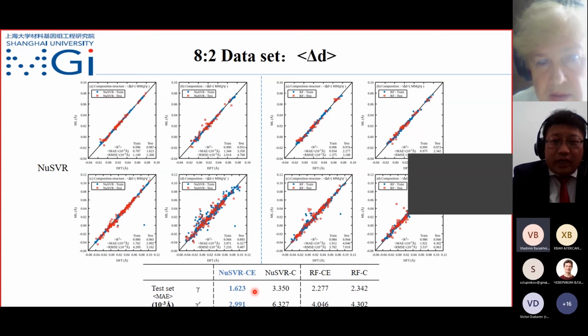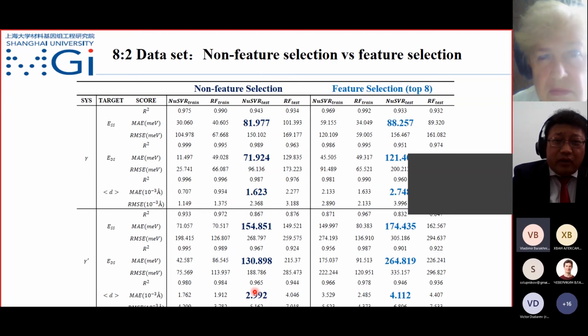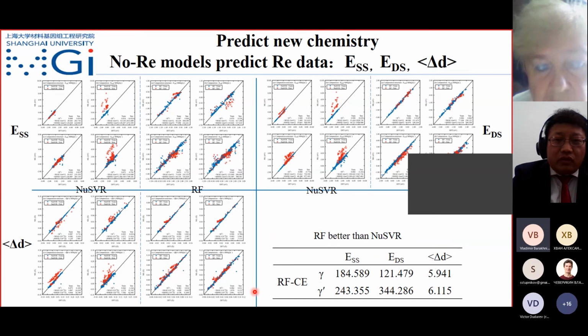And we also calculate the bond length change, which reflects the local distortion of the lattice. And this is very accurate. It's 10 to the minus 3 angstrom. So this is more than enough for the structure prediction. And we also compare our performance with feature selection and without feature selection. It turns out, in this case at least, without feature selection performs better.